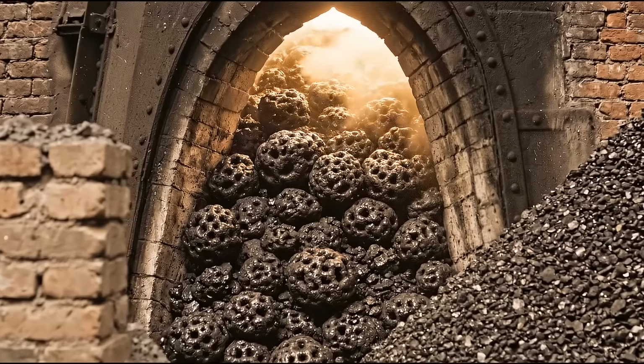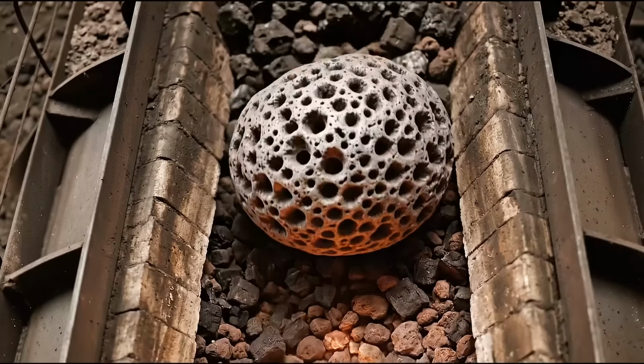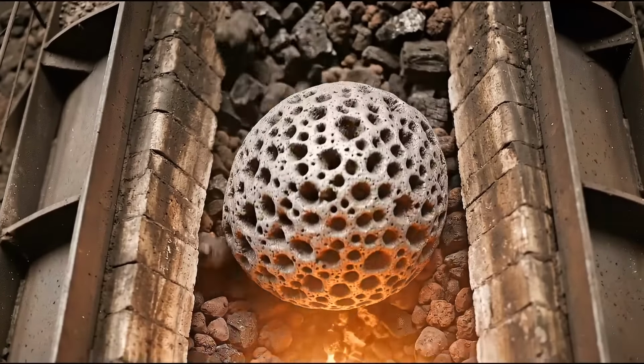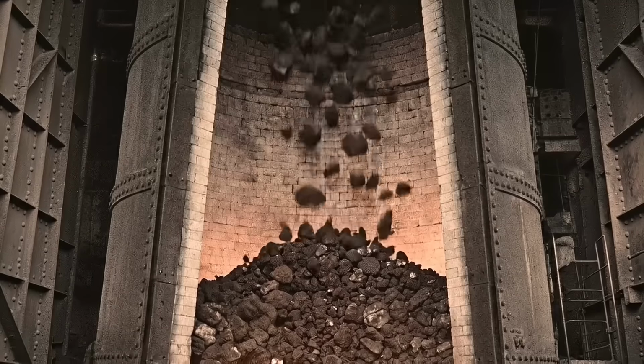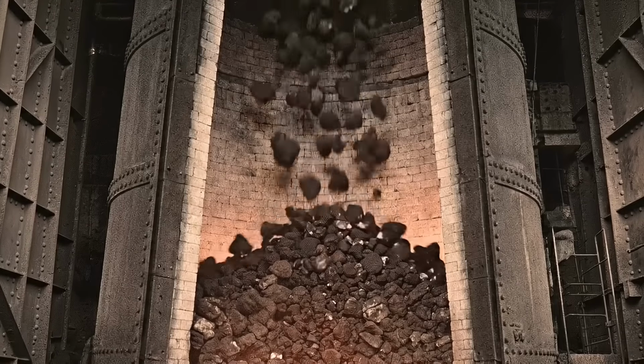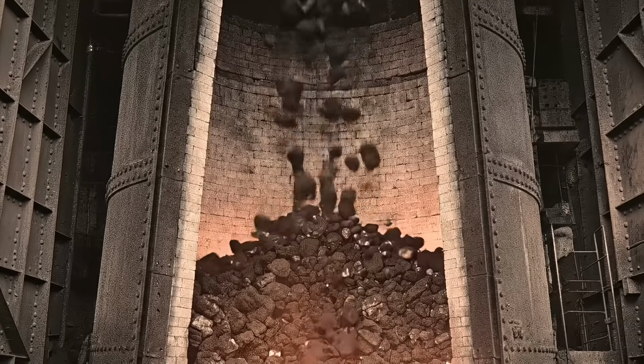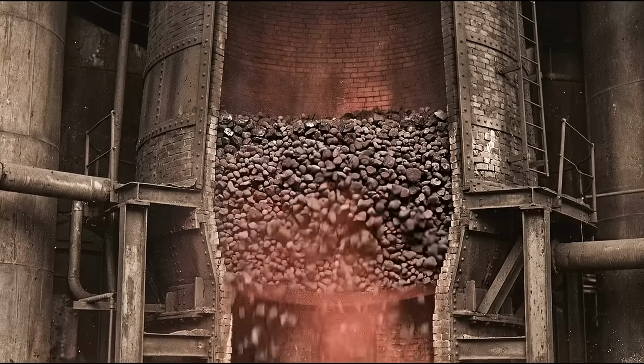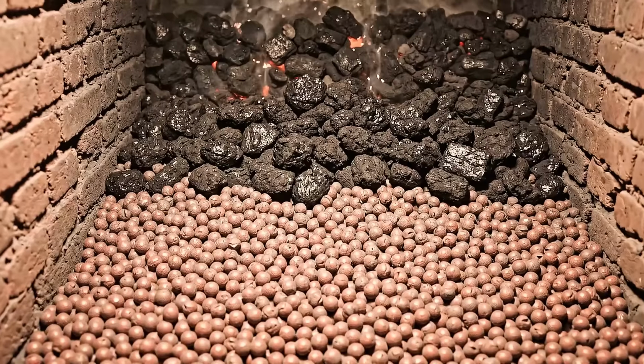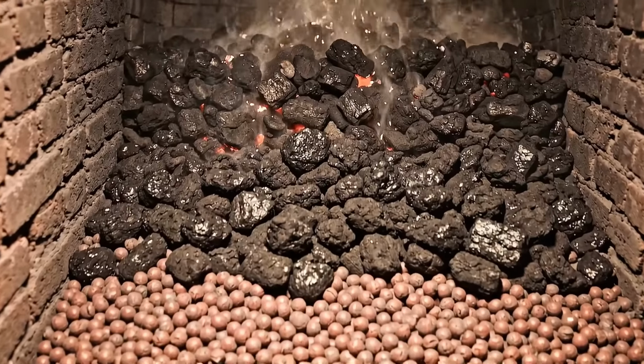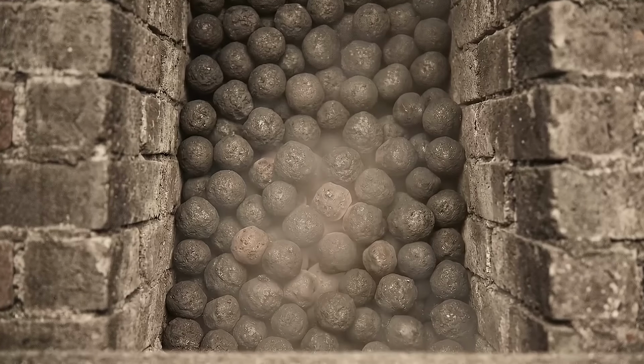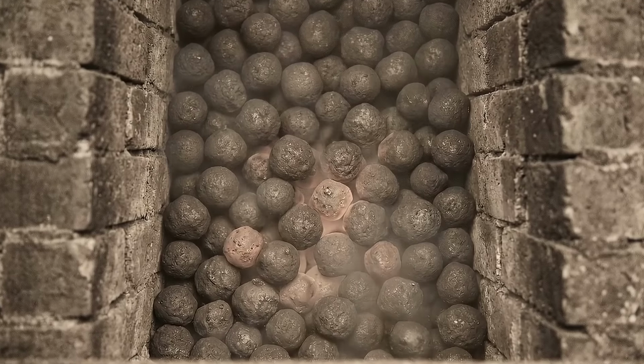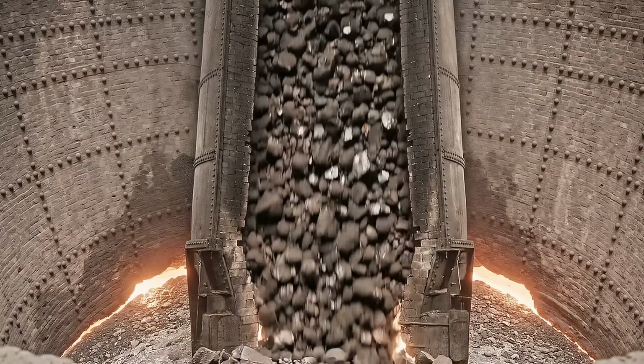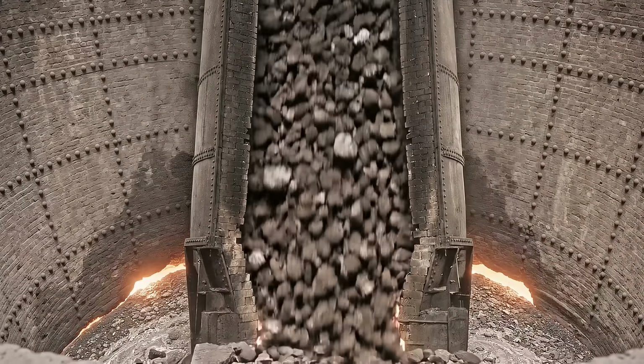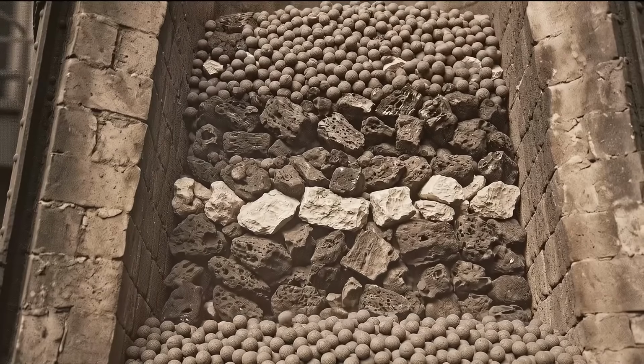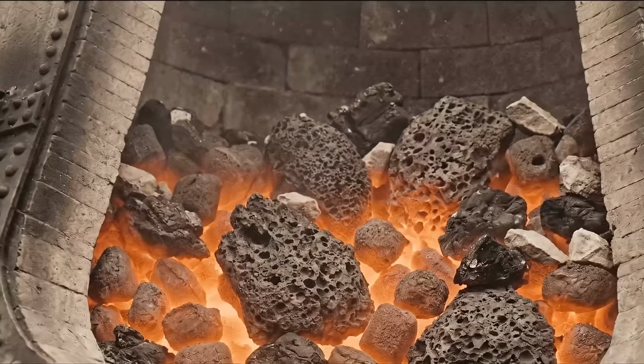At first, the reduced iron is still solid, a spongy mass working its way down through the hotter and hotter zones of the furnace. In the upper shaft, where temperatures sit between 400 and 800 degrees Celsius, the indirect reduction zone does most of the chemical work. The rising carbon monoxide gas passes through the descending ore pellets, and the iron oxide goes through a series of stepwise transformations, from hematite to magnetite to wustite, and finally to metallic iron. Each step strips away more oxygen, but the iron is still solid here. It has not melted yet.